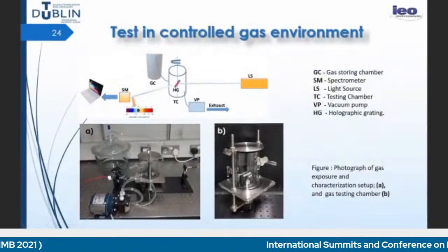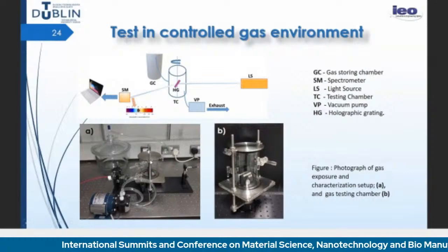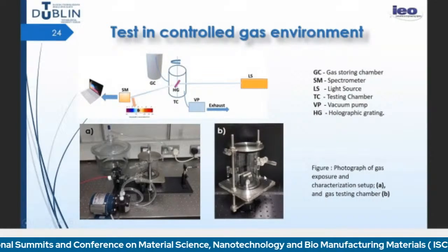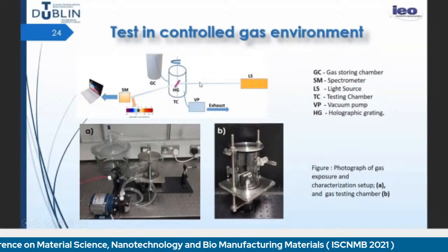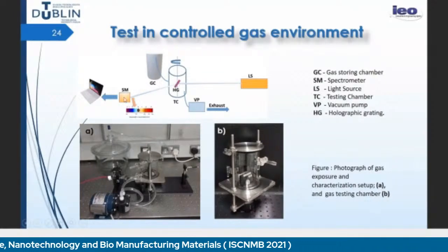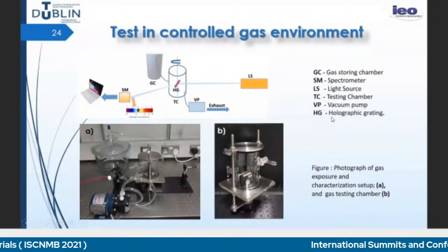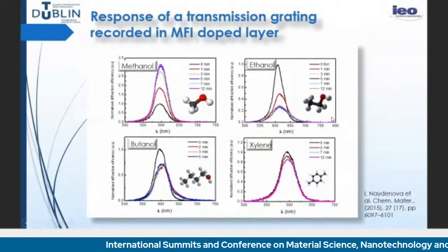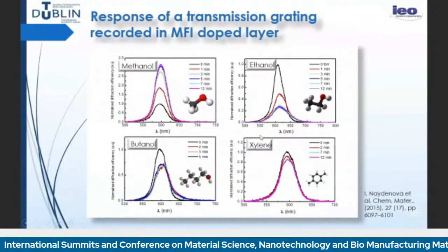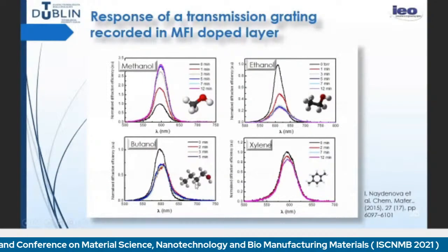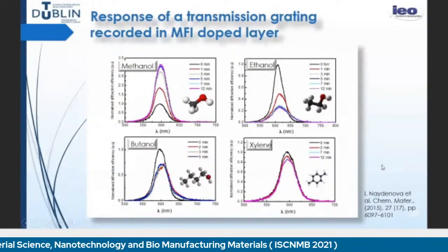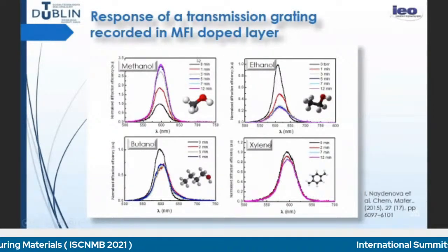So this is our control test environment. This is the chamber where we mount the hologram, then we send a white light and we look at the first diffraction order. And the light is sent to a spectrometer, and this is what we observe for different molecules as they become larger and larger. So this is methanol, ethanol, butanol. The molecule becomes larger. Also, we have used xylene, which is a different size of molecule. And what we have observed is how the spectrum changes over time.